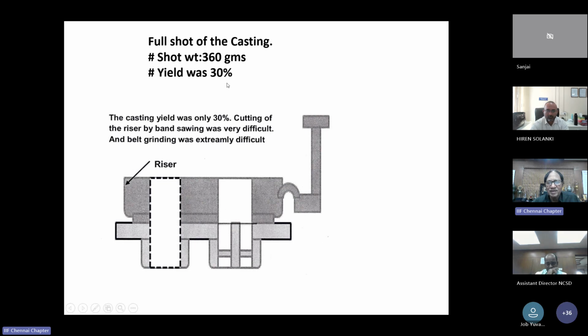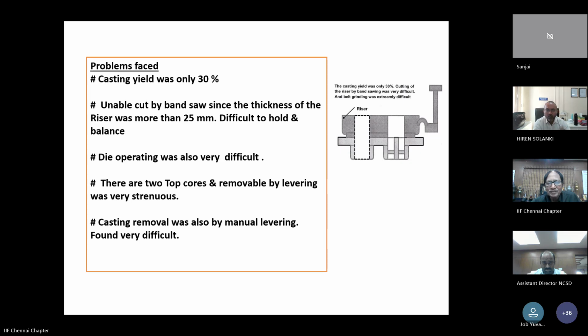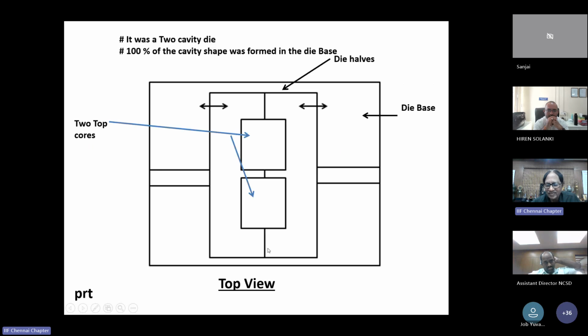Not only the yield problem, operating problem was very heavy operating. So the hell to operate. This is also very difficult because this is a 25 mm thickness all over the area, and the casting is hardly 10 mm. Holding it by hand and then sawing it by bandsawing is very difficult. It has also got 2 top cores. Very difficult to work. I will show you the die construction.